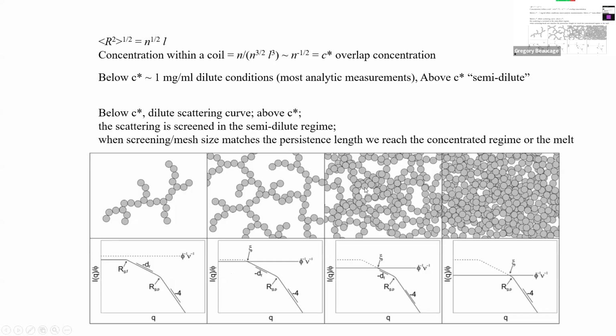And as the concentration goes up, those holes get smaller. So that kicks this Q, which is one over size, to the right. And this just continues to go down. The rate at which that goes down with concentration tells you how the chains are interacting. It gives you the thermodynamics, like the free energy of interaction between the chains. So it can be measured. You can measure that, right? So that's a way to measure how the chains interact, how they pack. If it's not a Flory, it's not random, and you're going to have charges between these things, and you get a peak in this. But the same thing happens. It still diminishes, and there's still an interaction.